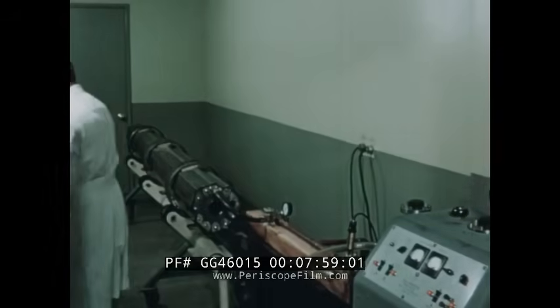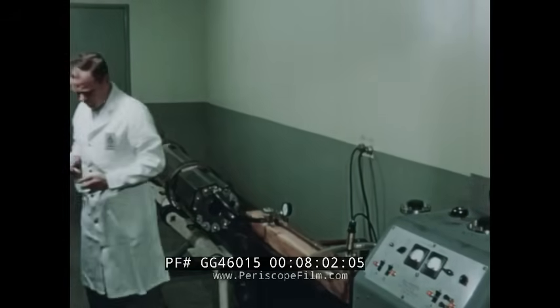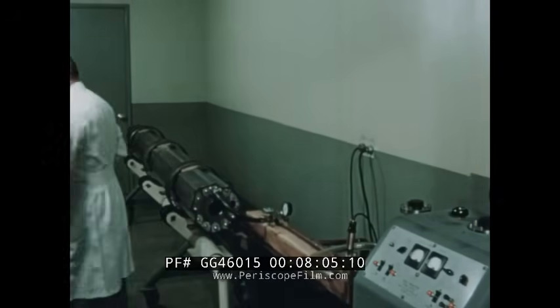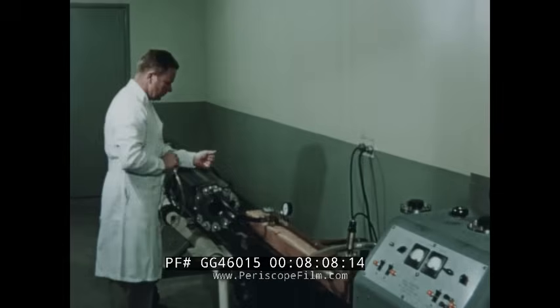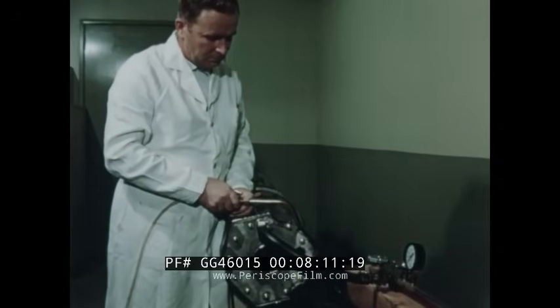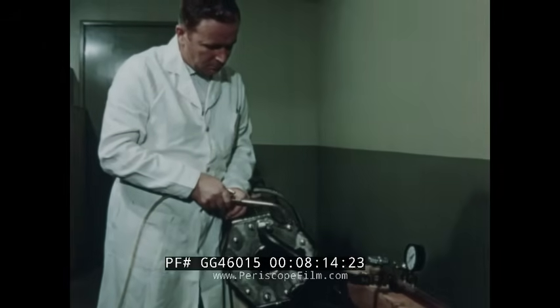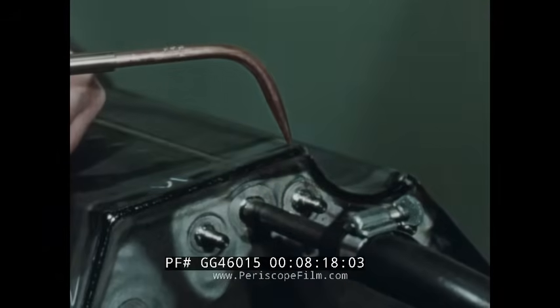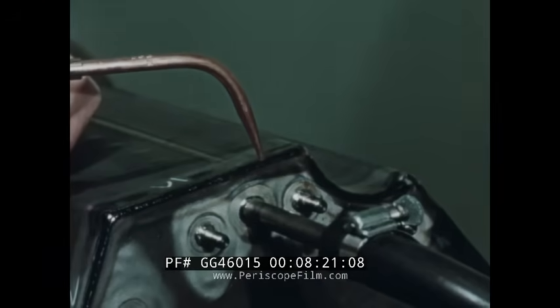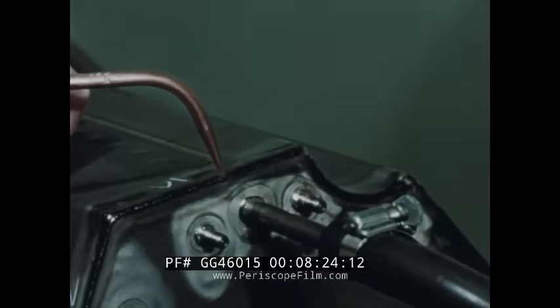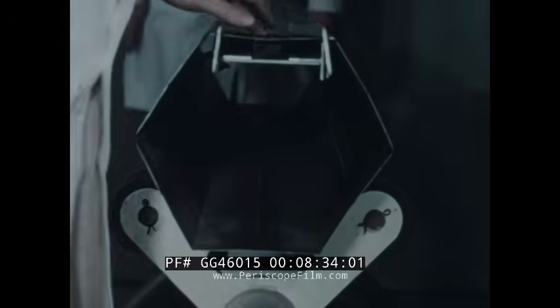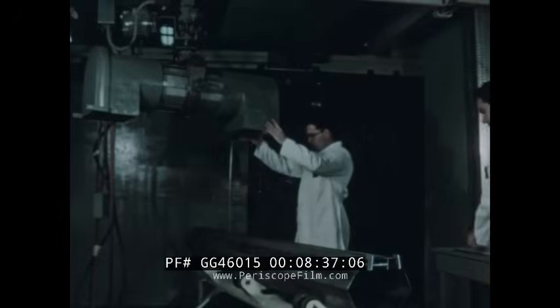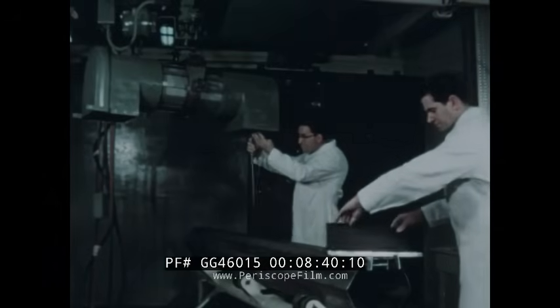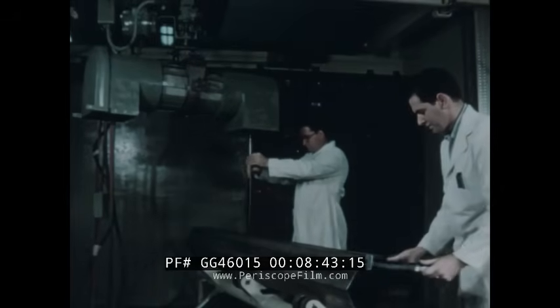The main purpose of the moderator can is to isolate the graphite from the sodium coolant. A leaking can would allow absorption of sodium by the graphite, causing excessive neutron losses. Each can was sealed, evacuated, and all welds helium leak tested. The welds were also x-rayed to check for porosity and contamination. Any faulty portions were marked, re-welded, and x-rayed again.